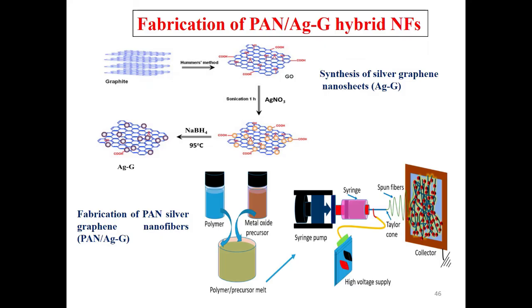Next is the fabrication of PAN AGG hybrid nanofiber. Here graphite is taken and the Hummers method is applied for the synthesis of graphene oxide. In situ synthesis is done for the synthesis of silver nanoparticles. Sonication is done, and because of that process the silver nanoparticles get doped over the surface of the graphene sheet, and that is called silver grafted